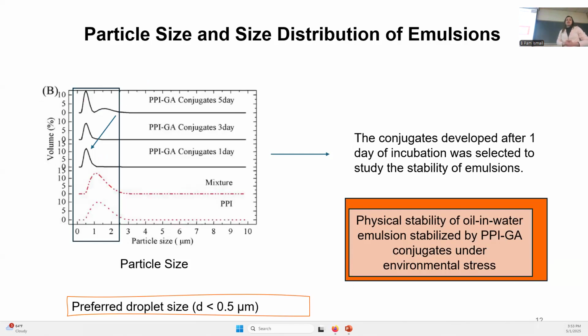Then they produced the emulsions. They made emulsions with all of these samples and looked at the particle size. The conjugates that were developed after 1 day of incubation were selected to continue with the stability study because they presented the smallest particle size. Particle size for an emulsion is important because a smaller particle size can reduce the rate of creaming, make it a clearer and more homogeneous emulsion, and reduce the rate of coalescence.